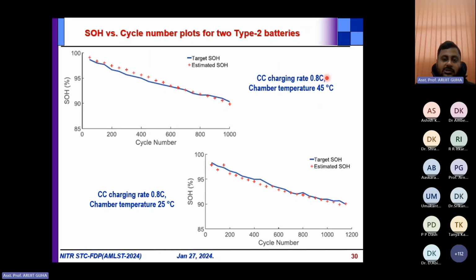So this corresponds to a charging rate of 0.8 C at chamber temperature 45 degrees, and this is at chamber temperature 25 degrees, keeping the charging rate fixed at 0.8 C. Okay, so you can see they are very close. You can see the estimated and the target values.